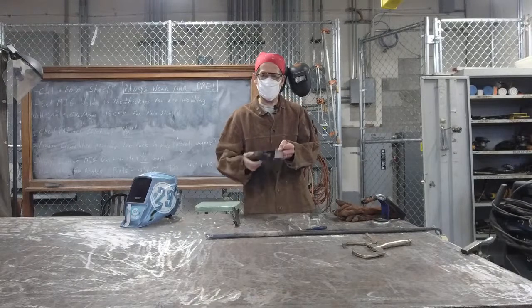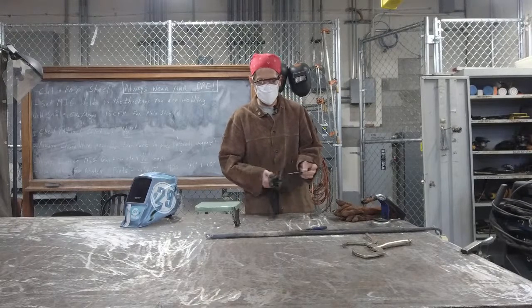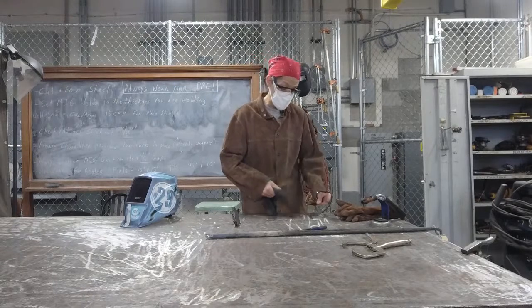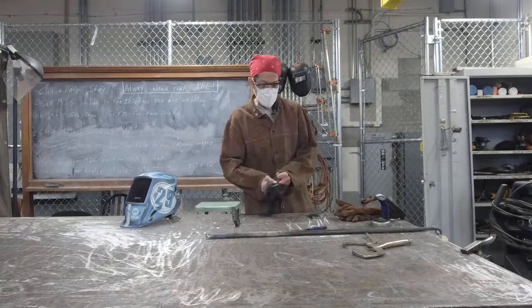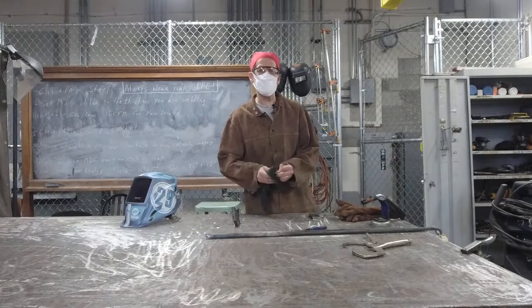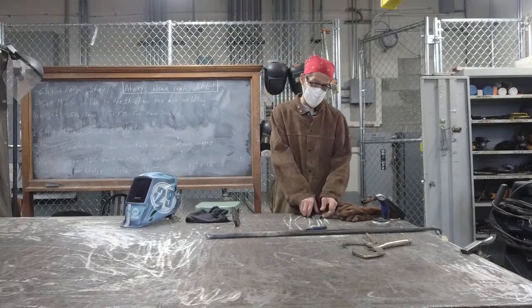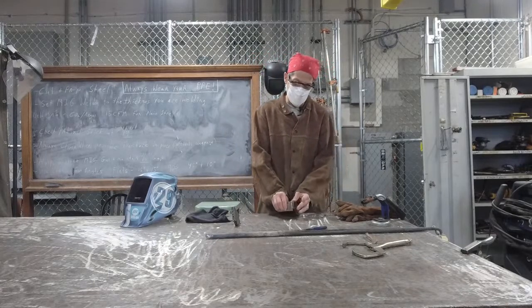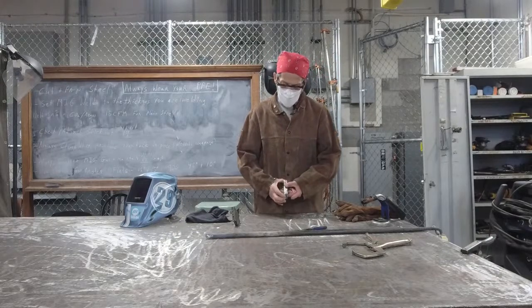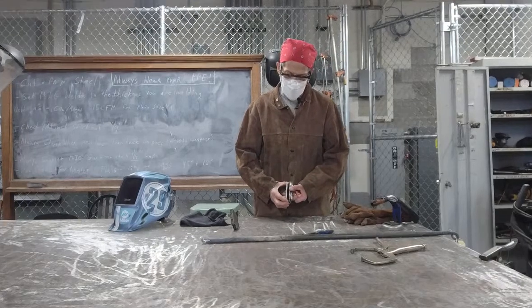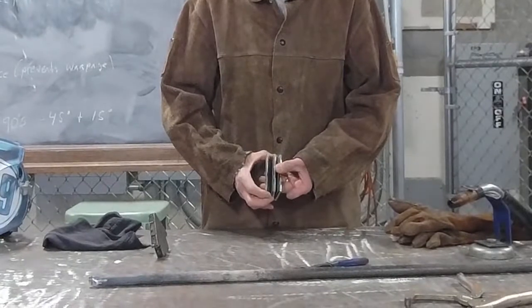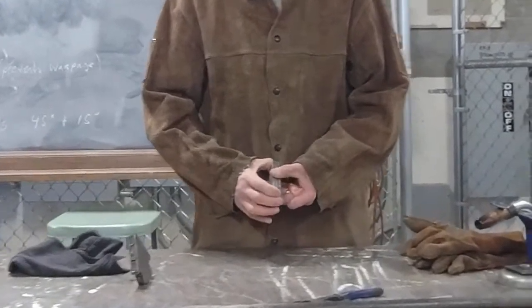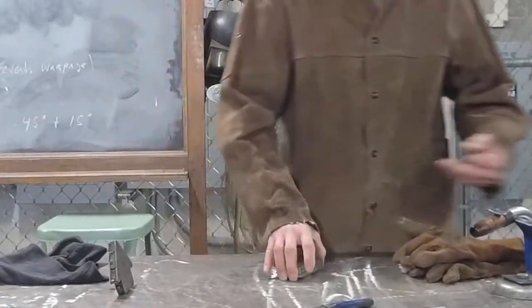This particular steel, the bandsaw blade, 15N20, it's made into bandsaw blades. That's already clean. Because it has such a high nickel content, it's corrosion resistant, so there is no need to grind it off. So you can see I've alternated my layers. I have 3 layers of the 1080, 2 layers of the 15N20. So I have a 5-layer stack.